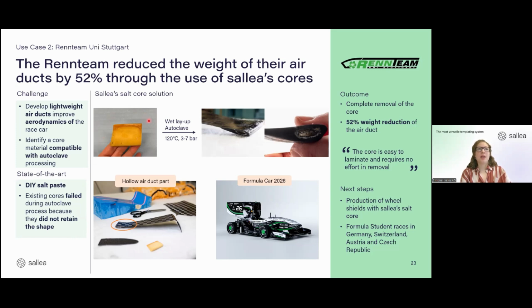And here you see an example of a core that we produced for them. So again, here this is 3D printed. And then they used it to do a wet layup and an autoclave process that was also at 120 degrees, 3 to 7 bars. They managed to make a part that is actually quite thin. And you can see here, so it's kind of this part that's where the core was in. They made kind of small openings and managed to get the full core out for this part. Here you see even the whole part a bit zoomed out. And this part is actually part of their race car that they are using this summer.